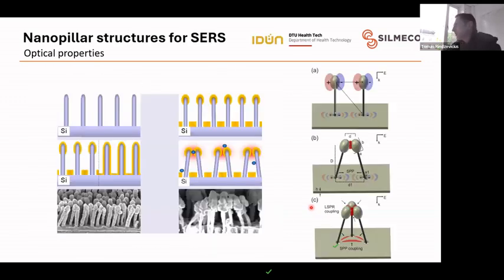And now we turn to trying to understand why they are performing so well. Maybe we can even do better. And here on the left-hand side, you see basically our first attempt, when pillars looked more like pillars. So you have a more uniform coating of gold here, like you see here. But it turned out that this is not optimal for SERS. So we could not get high enhancement, and probably because you have a uniform metal and you prefer to have gaps and more localized structures instead.